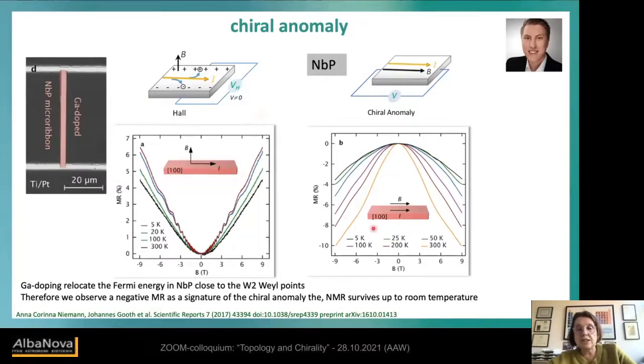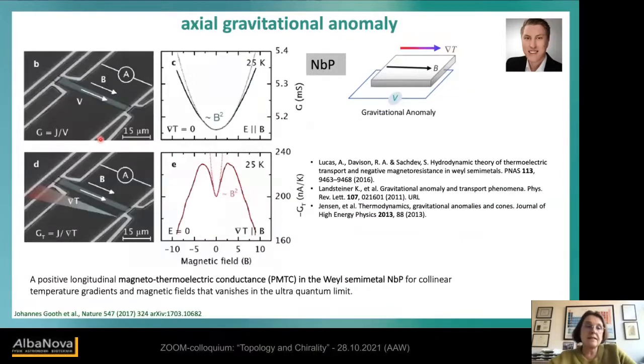And then we switched the magnetic field, and we saw, really up to room temperature, a negative magnetoresistance effect in this compound. So this was already good, because it showed that our micron ribbon shows the expected properties. And this then motivated us to do the second experiment, the prediction from Subir Sachdev and Karl Landsteiner and others,